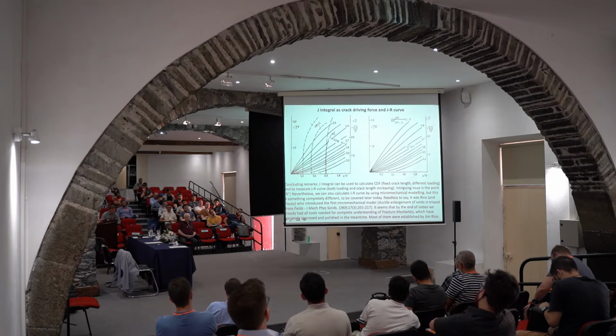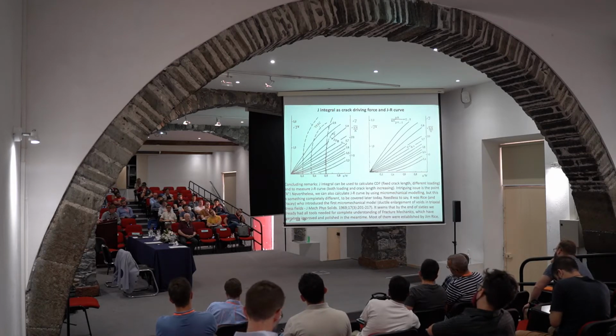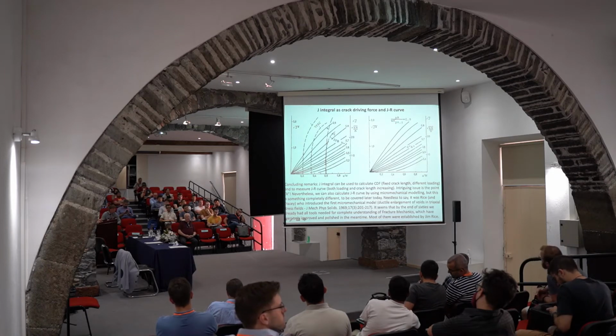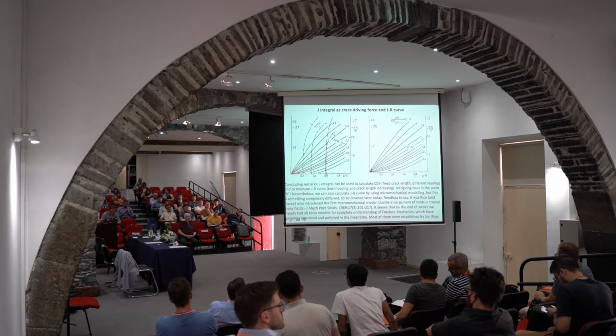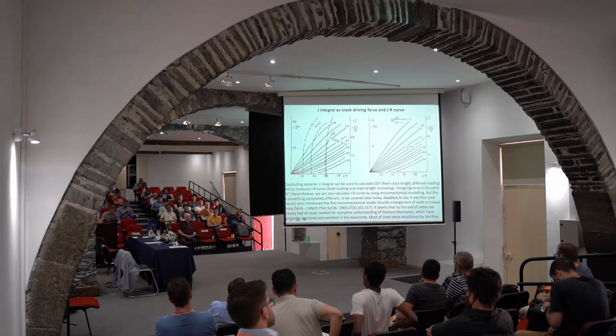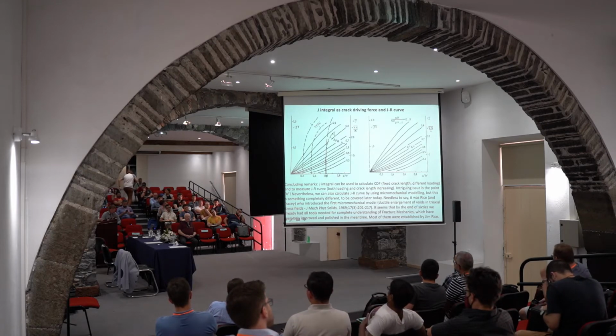In these three cases, we don't have any critical pressure. This pressure vessel can sustain pressure that would cause stress equal to yield stress, and still the crack will be stable. It will not grow.